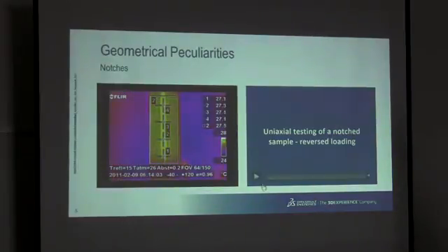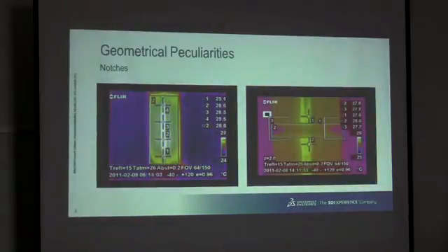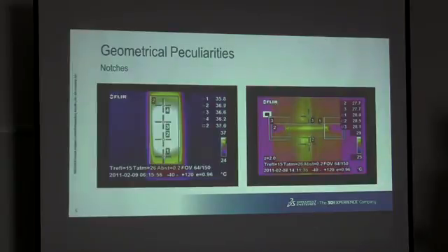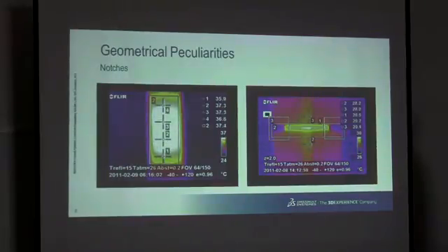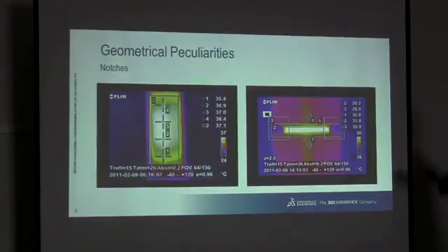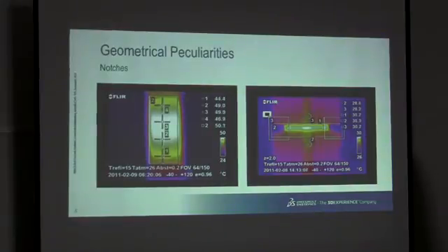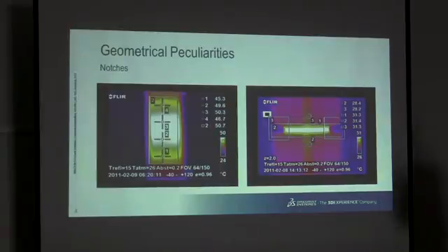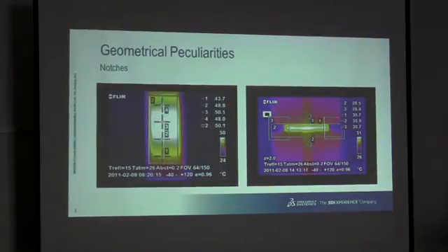But let's look at this thing instead, which is the uniaxial testing of a notched sample, where we're zooming in. At the beginning, we have a fairly homogeneous distribution, and after a while, you can also possibly see the viscoplastic or the constitutive appearance of the lagging strain. But what happens is that all the heat is focused to the notch, and this serves as a plastic hinge. That's where all the heat goes, and that's why.